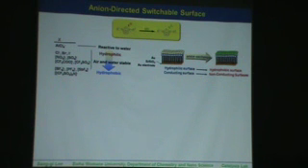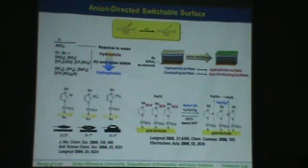So we thought it may be possible to transfer this anion-directed tunable property to surface science. If we put some imidazole molecules on a solid surface, the surface property will be easily changed simply by exchanging the anions. For example, we first made some monolayers with hydrophilic anions, and if we change to hydrophobic anions, the gold surface became hydrophobic.